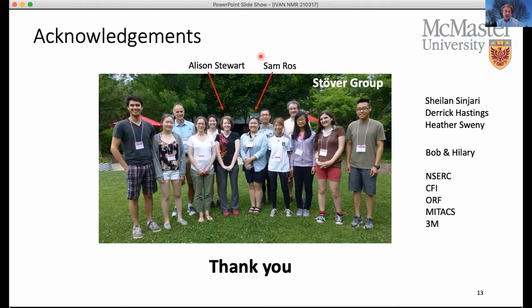Thanks, Darcy. Yeah, this work was done in a conventional solids probe, just without cross polarization, using little sapphire spinners, usually 5 millimeter — I think we used 3 millimeter diameter — with just O-ring sealed end caps. It's a little fiddly, they tend to break, and I usually make sure that I'm the one that breaks them, not my grad students. They appreciate that — there's enough at $100 each.